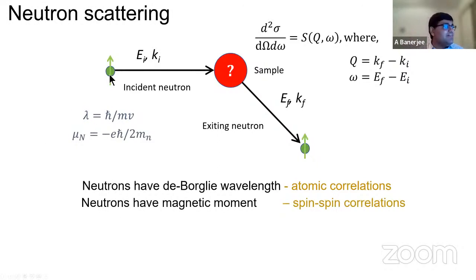But importantly, neutrons also have a spin moment. It has a spin half moment. And the spin half moment can interact with the spins in your system, and you can get a spin-dependent scattering. So there are two scattering mechanisms that neutrons give you. One is the spin-dependent scattering, and one is the spin-independent scattering. The spin-independent scattering tells you the structure of the material and the phonons, while the spin-dependent scattering gives you the spin structure of the material, the spinons, the magnons, and all the phenomena that I'm talking about here.